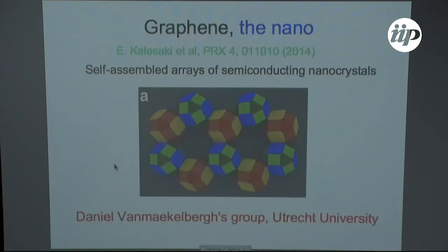Okay, so graphene, the nano. This is a theoretical paper with our results about this system. So here you get a sketch of what is happening. You make semiconducting nanocrystals of about 4.5 nanometers, little cubes. Nature doesn't like the edges, so the cube turns out spontaneously to be truncated. So you get surfaces 001, 110, and 111. It's just a truncated nanocube.